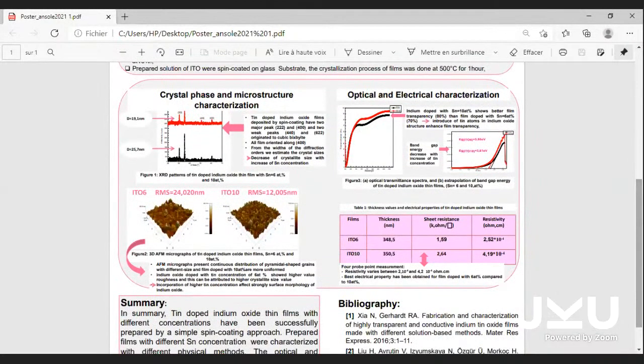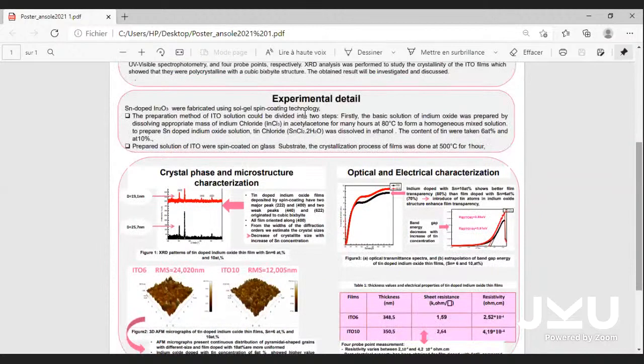The fabrication of ITO films was done in two steps: preparation of the solution by dissolving indium chloride in acetylacetone and tin chloride dihydrate in ethanol. The concentration of tin was taken as 6% and 10%. The prepared solution was coated on a glass substrate, and the crystallization of the film was done at 500 degrees for 1 hour.